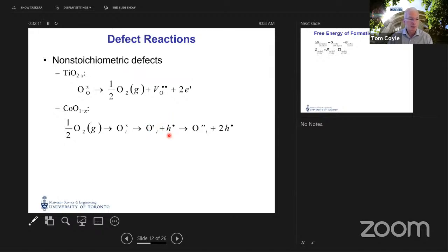Again, it may not stop there. The oxygen in that interstitial site may steal a second electron from the valence band to complete its outer shell, and thereby create 2 holes in the valence band. So there's a wide variety of possible defect reactions in oxides involving transition metal cations in particular.